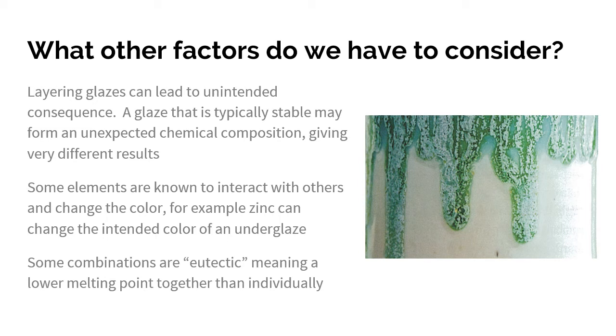Layering glazes. You may have made test tiles in your past. You may have experimented with mixing two different glazes together. And a lot of times when you're layering a glaze, you get some unintended consequences. A glaze that's typically stable may form an unexpected chemical composition when it's heated and is able to mix with other components in the clay body or in another glaze, giving some different results. Some elements can interact with others and change color. For example, if you are someone who uses underglazes, you typically put on an overglaze that is zinc free. Zinc tends to really change the intended color of an underglaze. It'll change purples to more blue, but especially with an underglaze, when you're hoping to have that integrity of color in the final piece, having something like zinc could impact the final color you're getting.